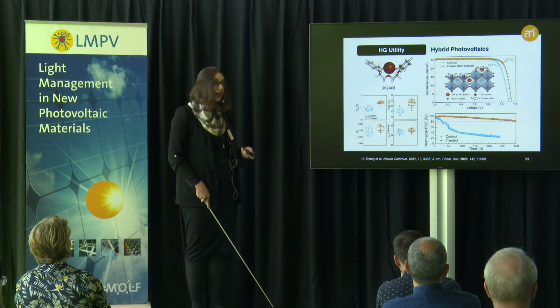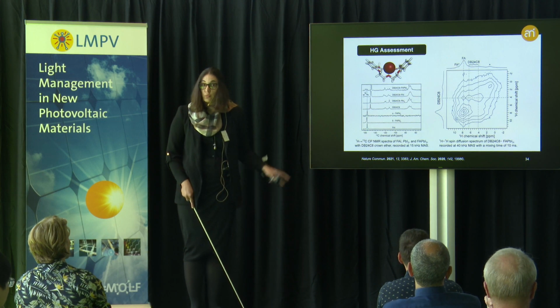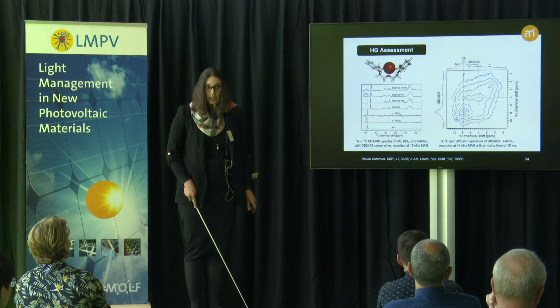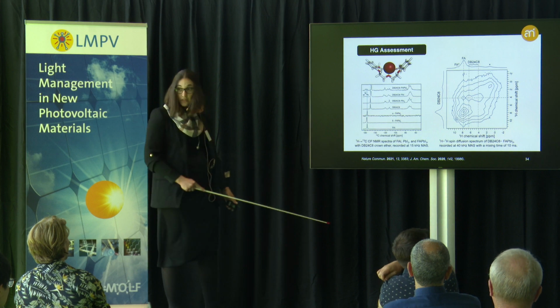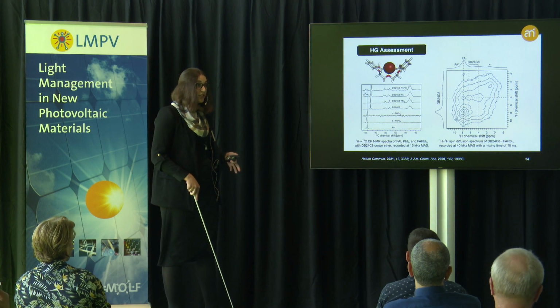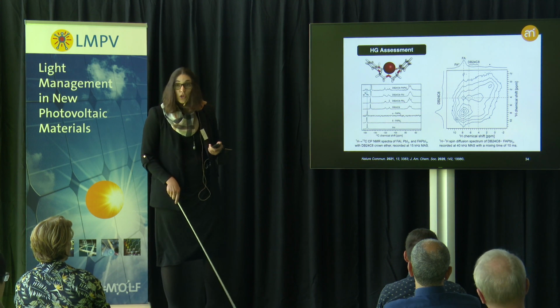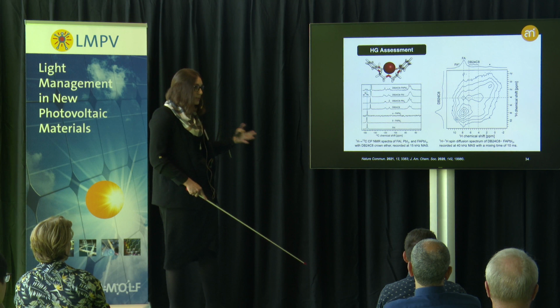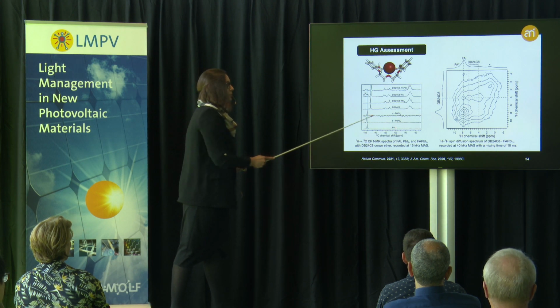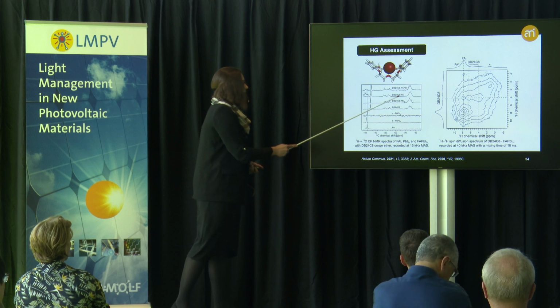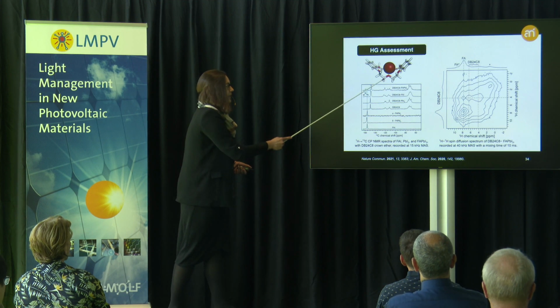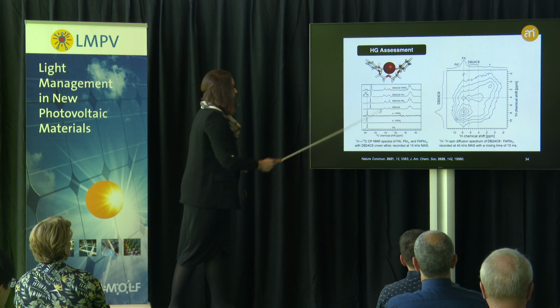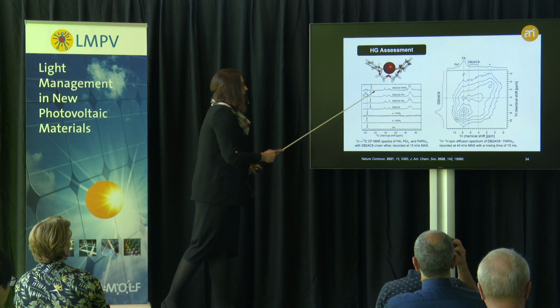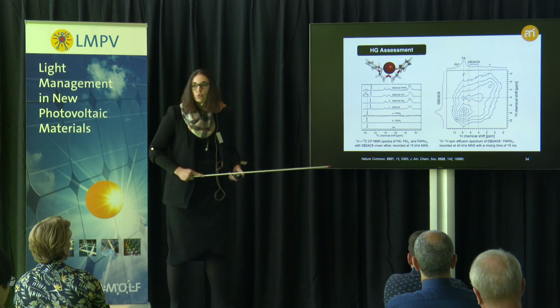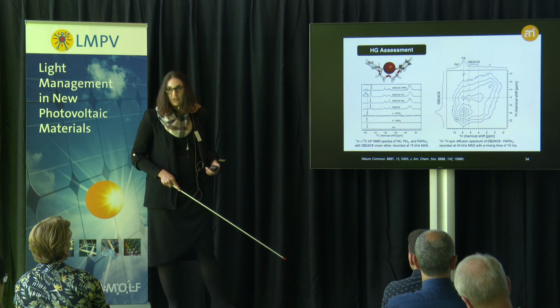And for this purpose, we rely on solid state NMR spectroscopy, which I would like to briefly illustrate here in terms of its capacity, which involves monitoring different NMR active nuclei, such as, for example, carbon-13, which has been proven very helpful in understanding the binding of A cations, for example, which can be done by monitoring the NMR spectra, carbon NMR in this case, of different precursors, resulting perovskite systems, as well as their mixtures with the host moiety, in this case the crown ether, illustrated here by this code DB24C8, which now enables us to identify different environments that would correspond to the system binding a specific A cation.